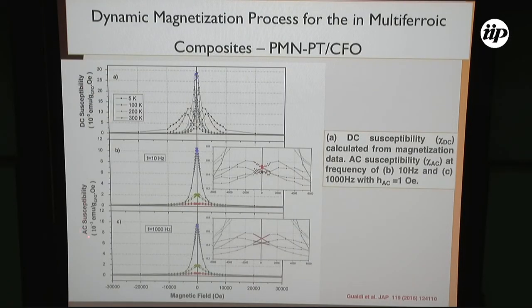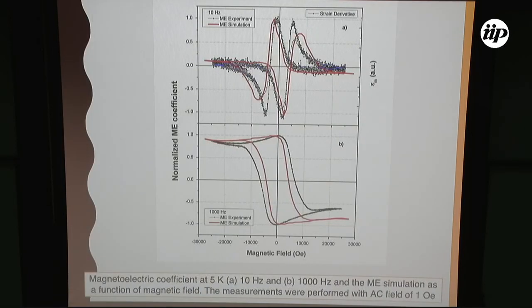So we compare this AC susceptibility as a function of magnetic field. This AC susceptibility at 10 Hz and 1000 Hz is very different from the DC susceptibility, which is the deviation of the magnetization as a function of the field. These are very different. One is obtained directly from the magnetization curve. The other is obtained by a direct AC susceptibility technique using 1 oersted at 10 Hz and 1000 Hz. When applying this model, a very good agreement is obtained at 10 Hz and 1000 Hz, reproducing the curve.